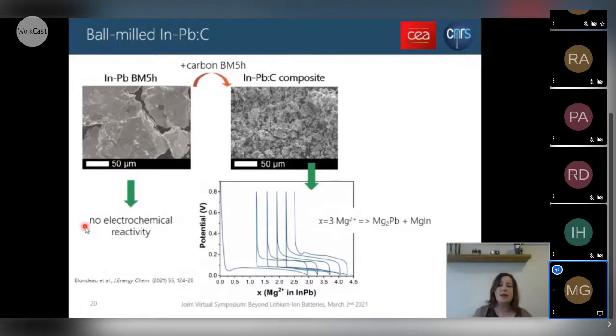They were too big. So to scale down the particle size, we added a second step in the milling process by adding 30% by weight of carbon to help, in fact, limit the welding and melting of the InPb particles. So here is what we obtained. As you can see, the addition of carbon really helps reduce the particle size by a factor of 20 to 40. And we get this InPb carbon composite, and we could finally get the electrochemical behavior of this InPb solid solution.